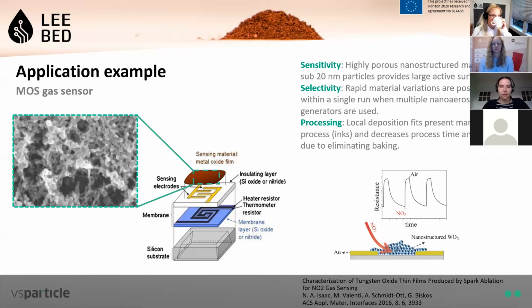And so the nanoparticles, or the active layer, are deposited on top of such a chip in an additive way. The active sensing layer is shown here in red. And in this example, the primary particles of tungsten oxide were amorphous with a size range of 10 to 15 nanometers, so really small. But as they were amorphous, they needed to be heated up, I think, to 500 degrees Celsius to become crystalline. And then they also grew to 30 to 50 nanometers.